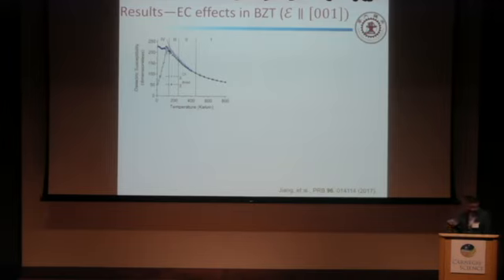Our Hamiltonian in BZT predicts a series of specific temperatures. The first one is Tm, about 130 Kelvin. The second is the critical temperature, T star, about 240 Kelvin. The third one is the Burns temperature, about 450 Kelvin. These temperatures are in good agreement with the experiment.